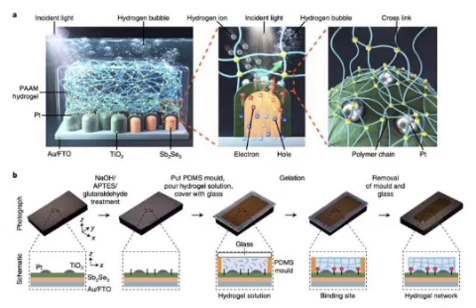They tested this layer on a photocathode made of antimony triselenide (Sb₂Se₃). A hydrogel-protected antimony triselenide photocathode exhibits stability over 100 hours, maintaining approximately 70% of the initial photocurrent, and the degradation rate gradually decreases to the saturation level. The structural stability of the TiO₂/Sb₂Se₃ photocathode remains unchanged beyond this duration, and effective bubble escape is ensured through the microgas tunnel formed in the hydrogel to achieve a mechanically stable protector.